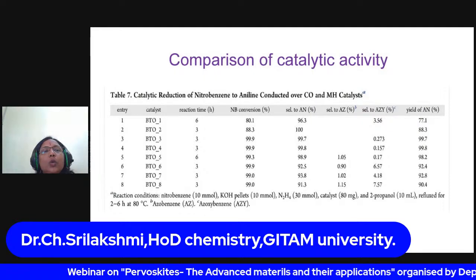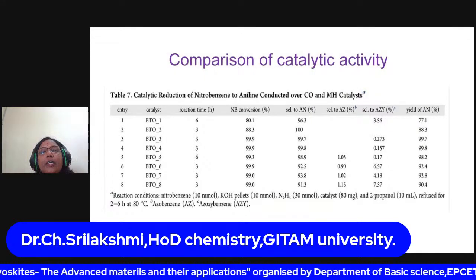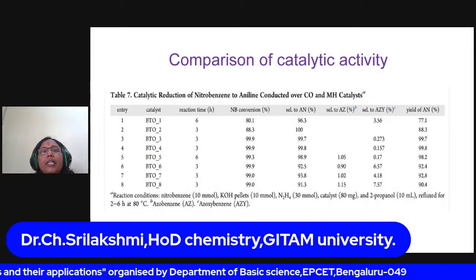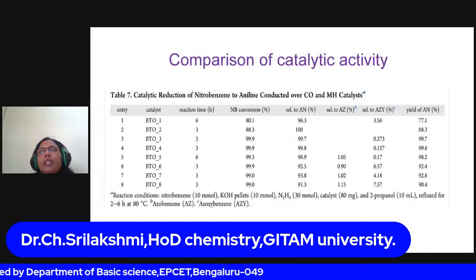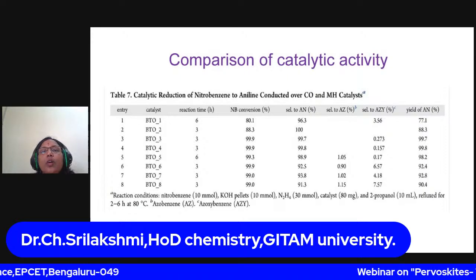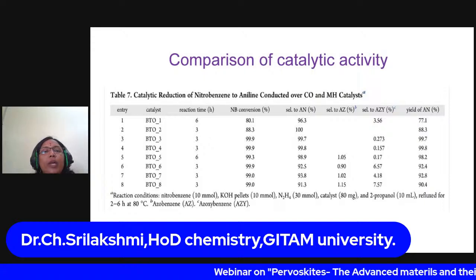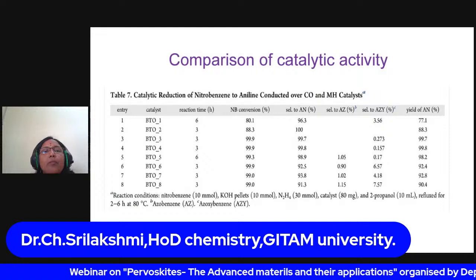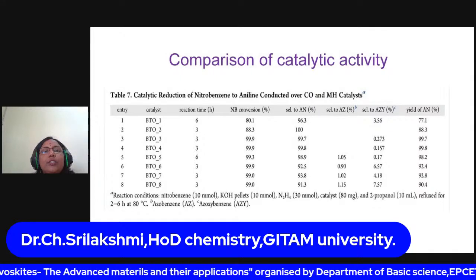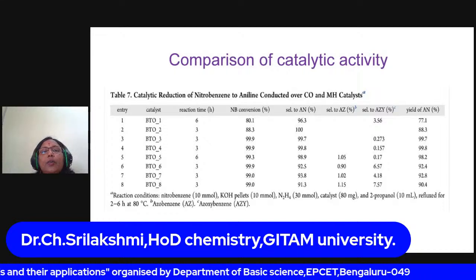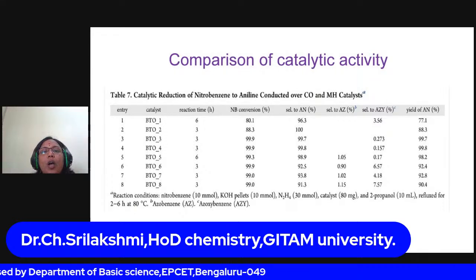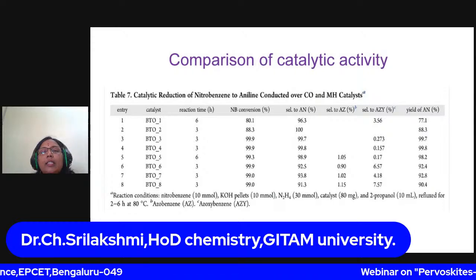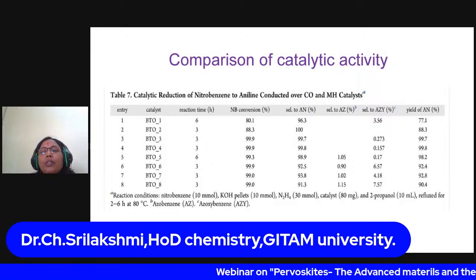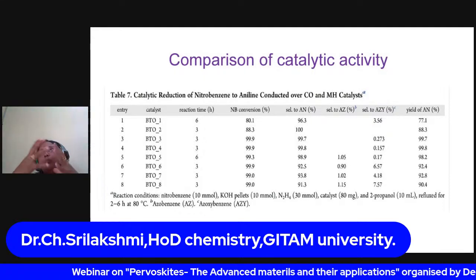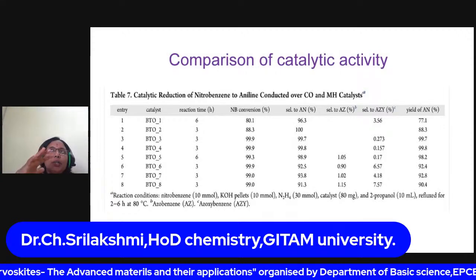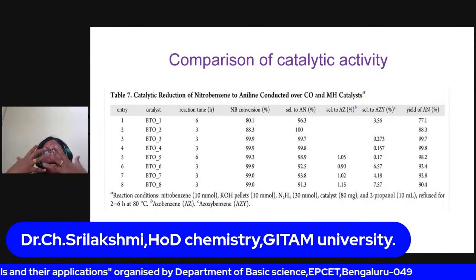Whereas for the chromium samples, the activity improves until 2.5 and after that remains constant. The same 100% yield is obtained at 0.5 chromium. If you take the microwave synthesized samples, BTO5 is the barium titanate synthesized using microwave. We can see 100% conversion and selectivity. After that, conversion remains constant and the selectivity goes down because of side reactions. Sometimes if we have a very active, highly porous material and we incorporate something into it, the catalytic activity will go down.